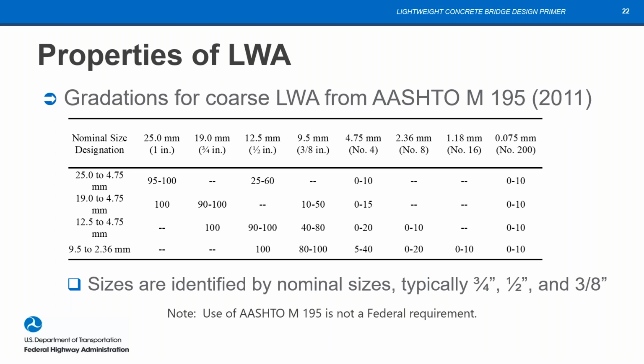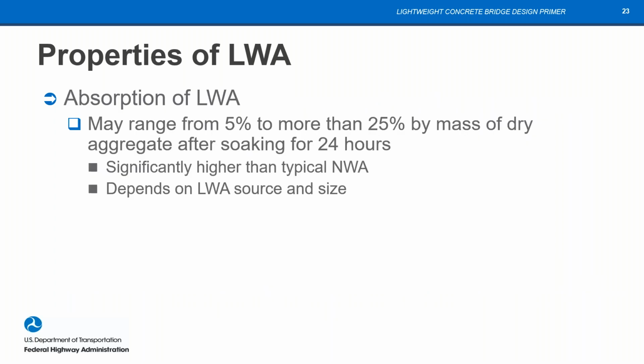The properties of lightweight aggregate, that is the gradation for coarse lightweight, are given in AASHTO M195. This is a chunk out of the table. It's not the whole table, but it's a piece of it that's showing the coarse aggregate gradations. We don't have gradations that are 57, 67s, whatever, that kind of thing. It's just 3/4 inch, 1/2 inch, and 3/8 inch, based on the maximum aggregate size. So there are specifications, just like for normal weight, that specify the gradation and other properties for the lightweight aggregate. There is also a gradation available for fine aggregate.